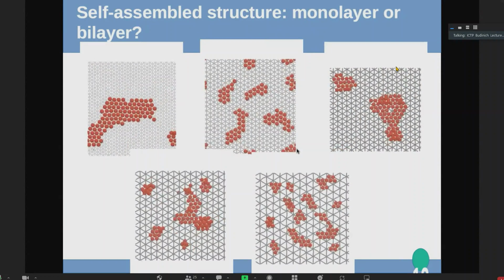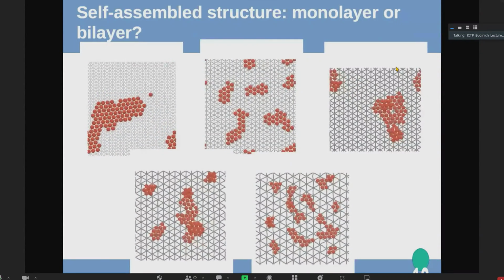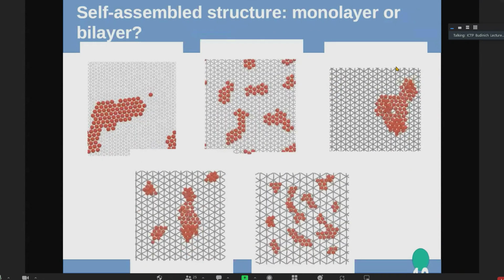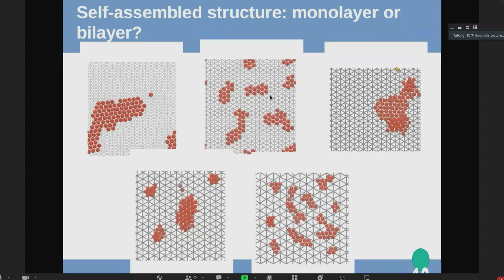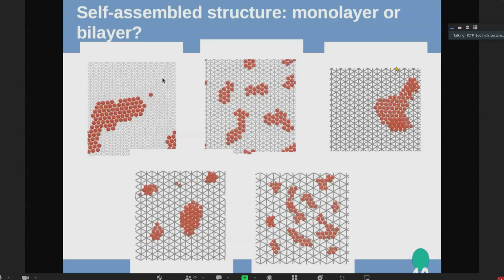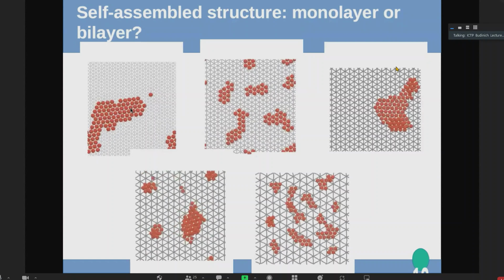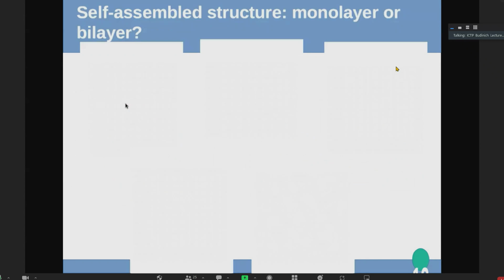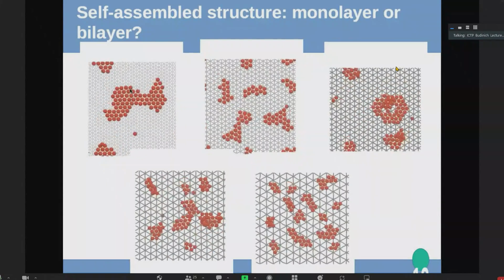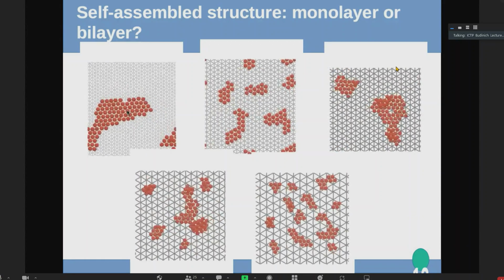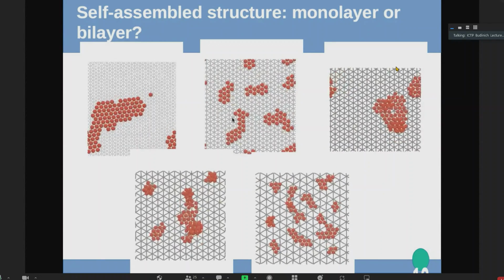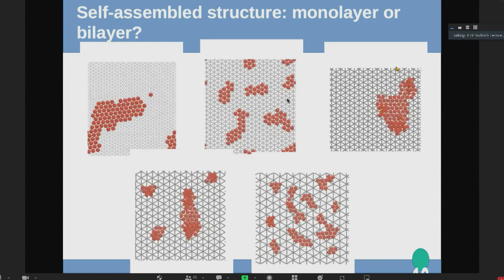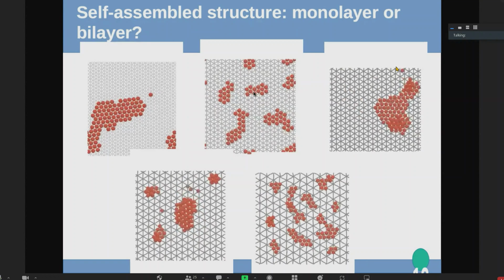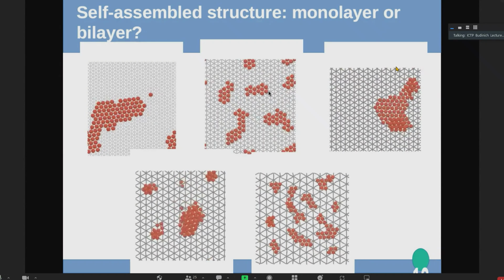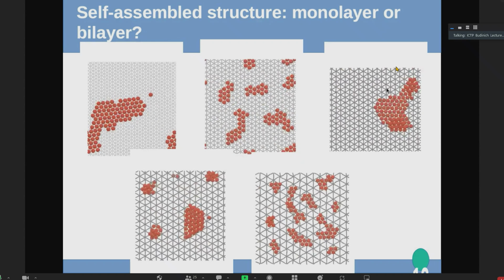And what was more interesting for us was the collective behavior of C60s on top of these two-dimensional structures. You see that with the small lattice size, we have easy movement for islands, and the islands can find each other and create an almost large island. But in the other systems, the trap is too strong, and the structure could not be extended to a very large lattice size.